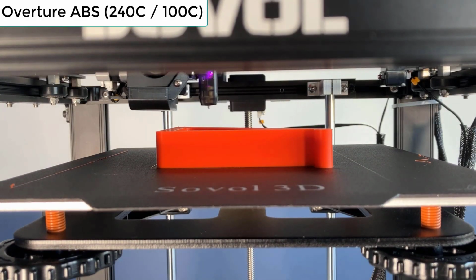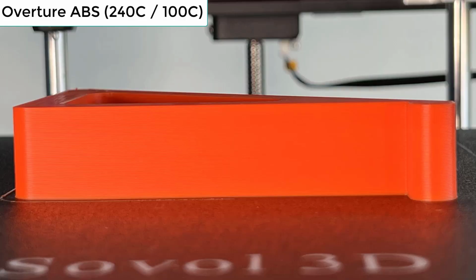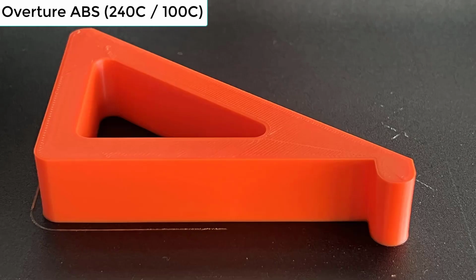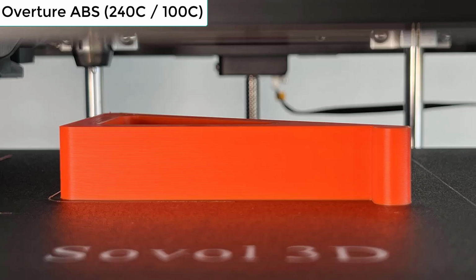The result is pretty great. The corners did not warp at all, and the layers are beautifully printed and very even. I can't find any issues with this shelf bracket, and I would say it's a perfect print. The fact that an open printer like this SV05 can print ABS with this result is actually quite impressive.